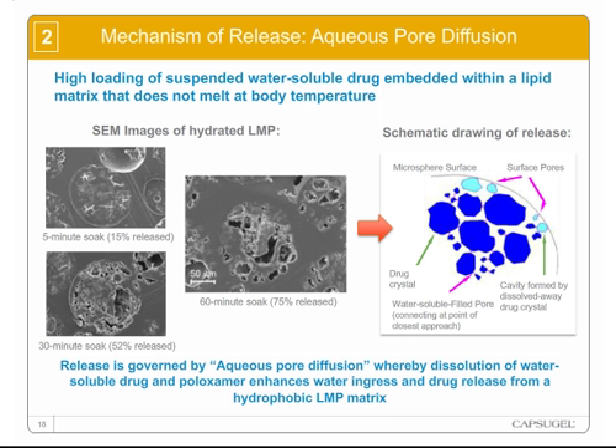After the target release profile was met, systematic in vitro evaluation of the LMP was conducted to understand and delineate the mechanism of azithromycin release on hydration of the LMP particles. As demonstrated here, SEM analysis revealed that pores readily form within the LMP particle as it is hydrated. These pores stem from the dissolution of the drug in the poloxamer near the particle surface, resulting in void spaces within the impermeable lipid matrix. And in turn, this forced drug diffusion to occur through these large voids and interconnecting small channels.